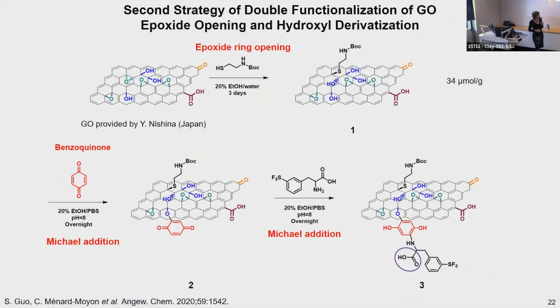The second strategy for the double functionalization of graphene oxide is this one, combining again the epoxide opening with the hydroxyl derivatization. And for the epoxide ring opening, we used not an amine in this case, but a thiol containing molecule, because thiols are also highly reactive towards the epoxide. They are highly nucleophilic. So this first reaction led to this conjugate. And then the hydroxyls were derivatized with benzoquinone. So benzoquinone has two double bonds that are highly reactive towards nucleophiles. So we could derivatize the hydroxyls in very mild conditions at room temperature.